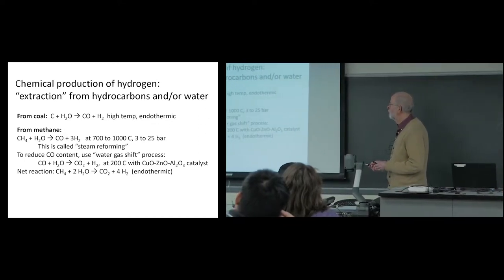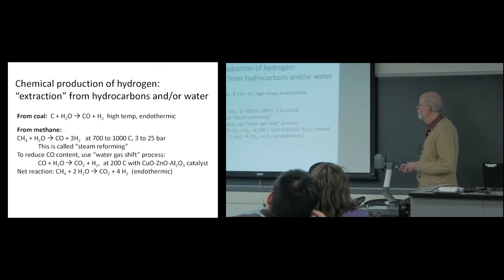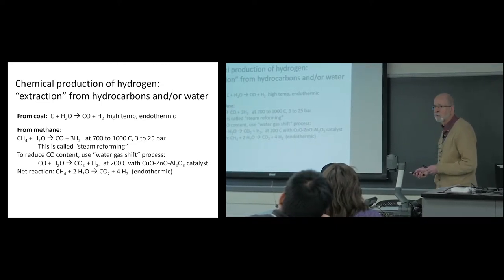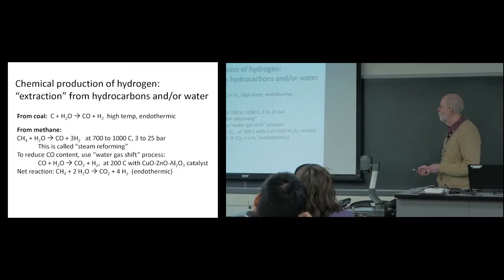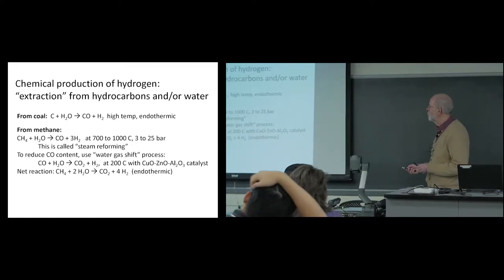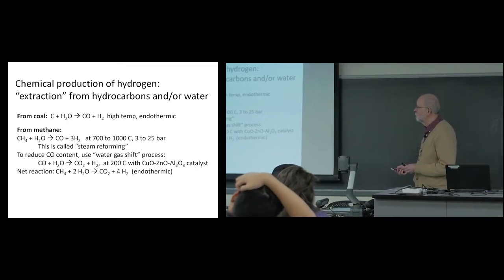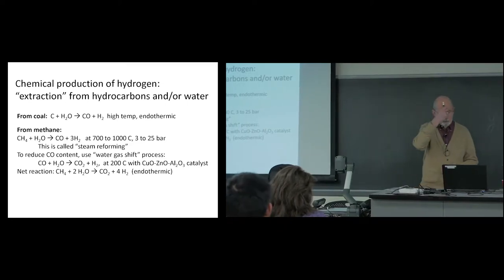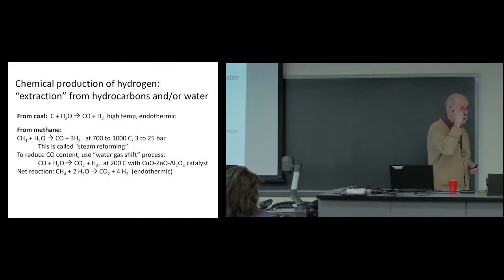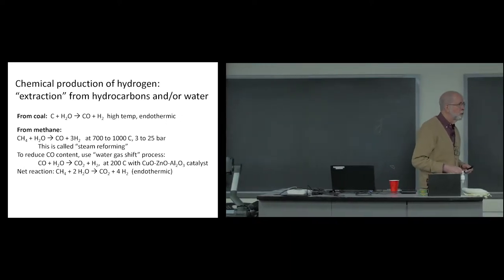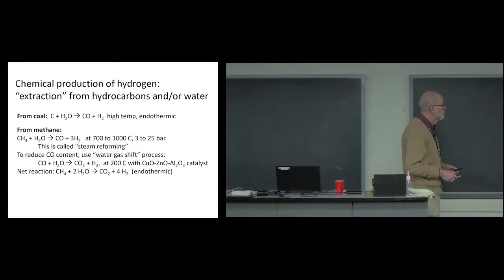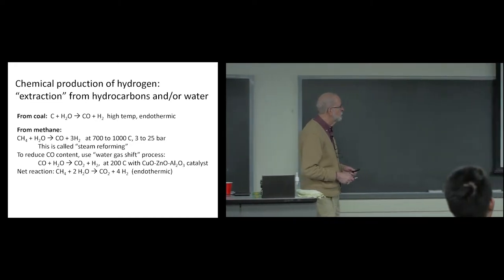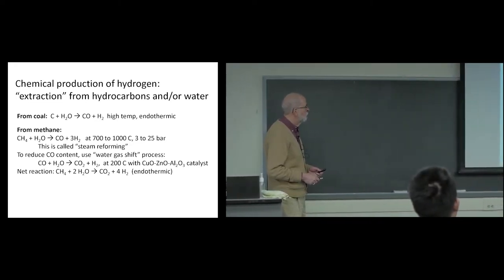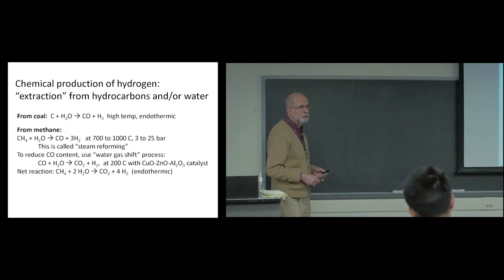Now, that's not where most hydrogen comes from anymore, not from coal, because you get much more hydrogen if you start with methane, natural gas, because the carbon already has four hydrogens associated with it. You combine that with water, and you make a lot more hydrogen at somewhat lower temperatures. This is called steam reforming of a fossil fuel into a lot of hydrogen and some carbon monoxide. Now, you also want to get rid of the carbon monoxide, so there's another reaction, the water gas shift reaction, where you take CO and water and turn it into CO2 plus more hydrogen. And you can do that at a low temperature with some special catalysts.